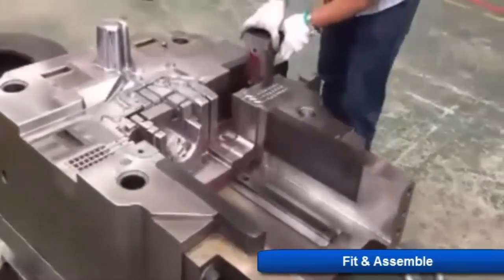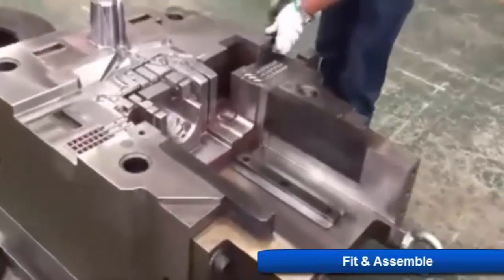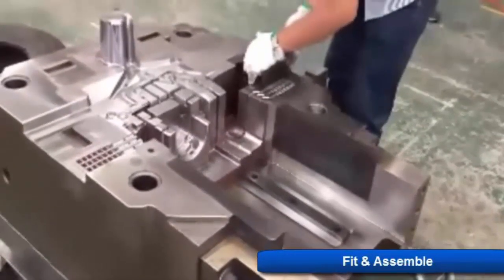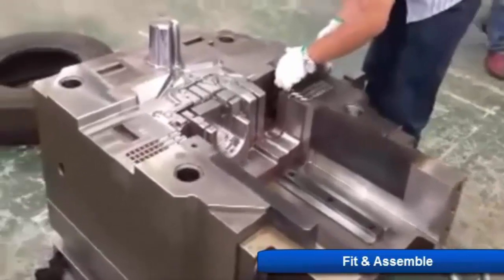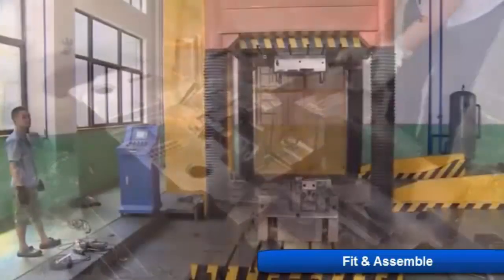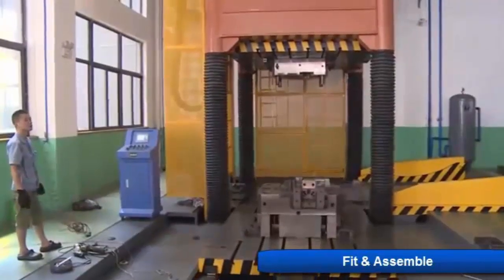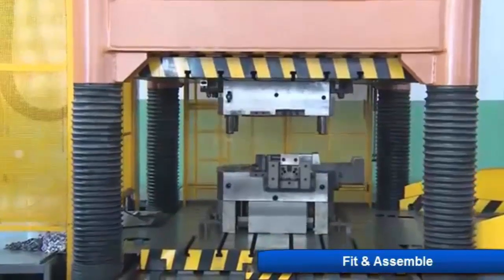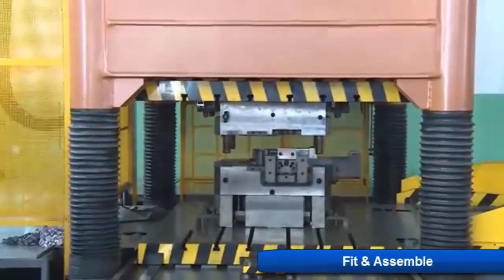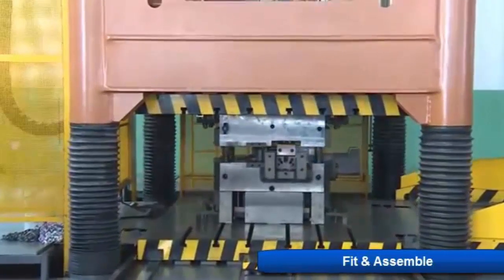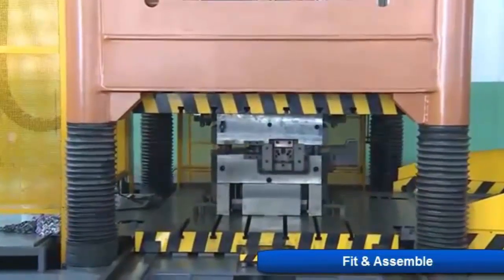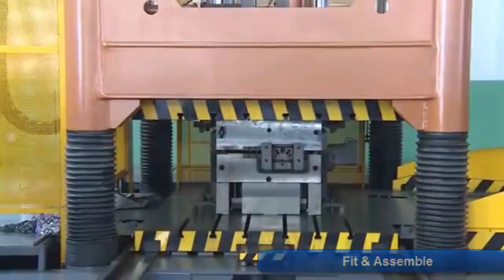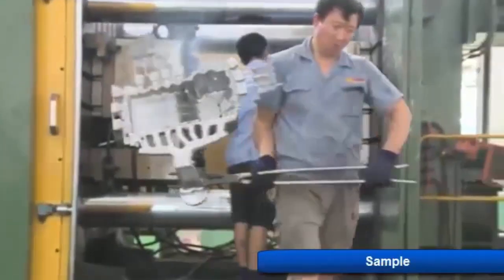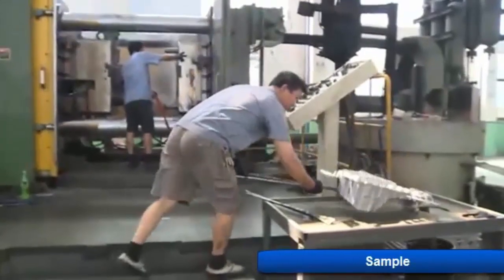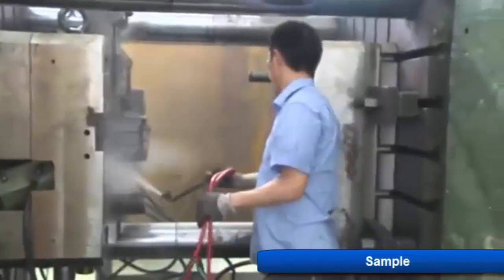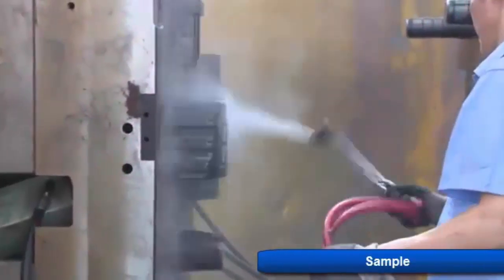They'll apply a blue dye to each of the moving components and then close everything together and check where that dye transfers to the other components. What you see here is an example of them putting everything together and doing the first initial fit. They're closing it slowly to make sure that if something isn't going to work, they don't cause damage. Afterwards they'll check that dye to see if it transferred properly. And then each one of our dies is going to go through a sampling process, whether it's made here or whether it's made internationally.